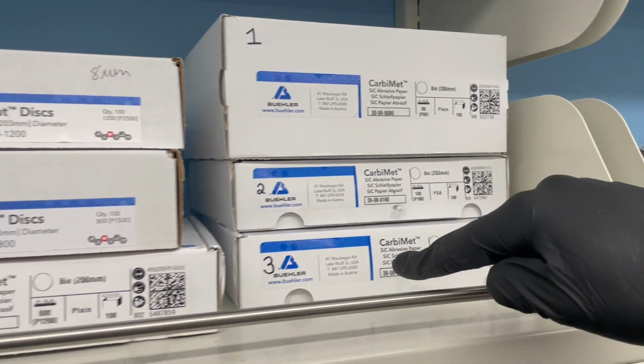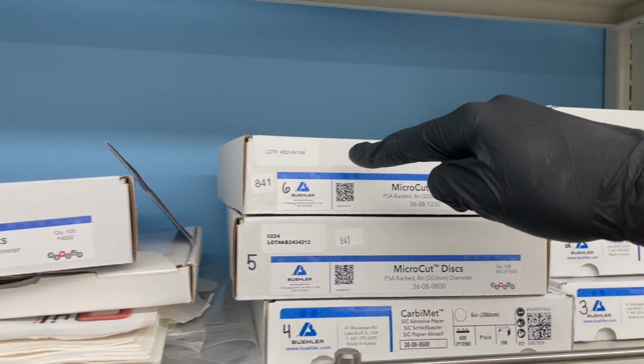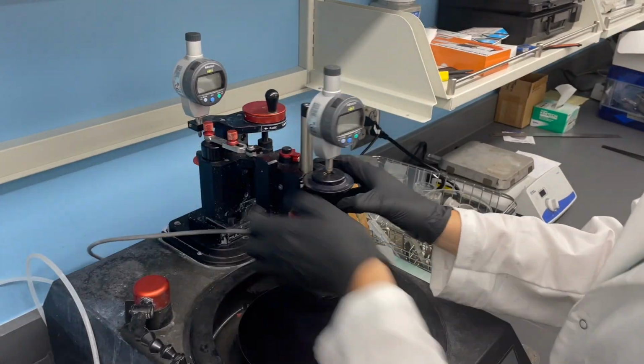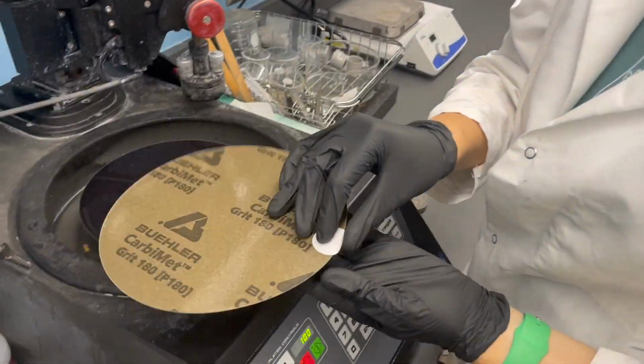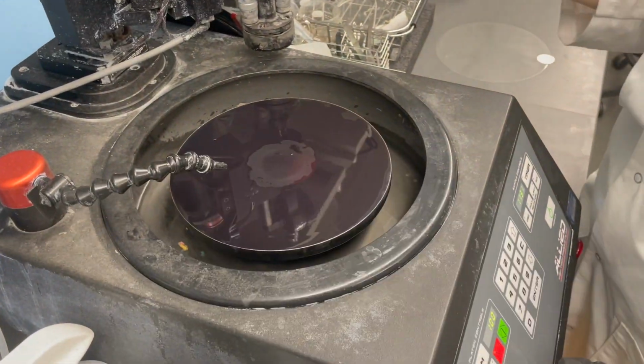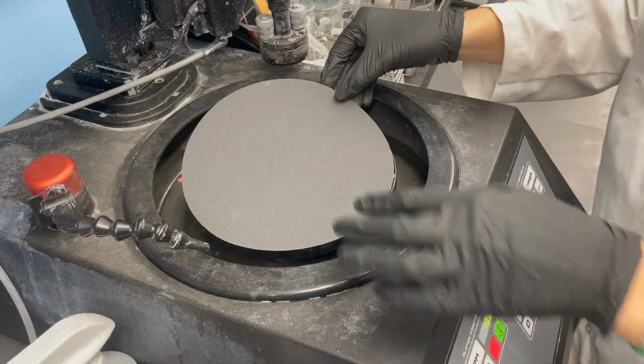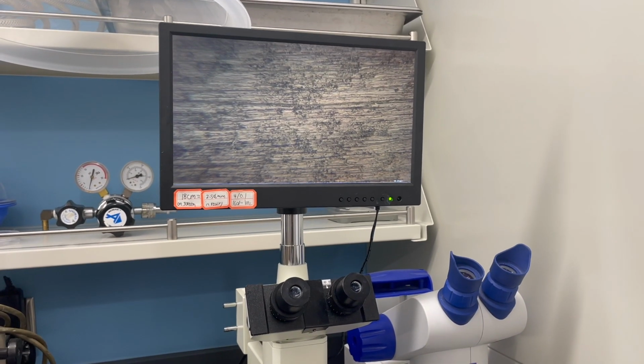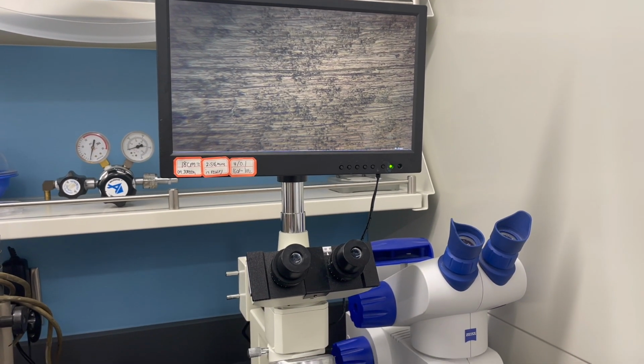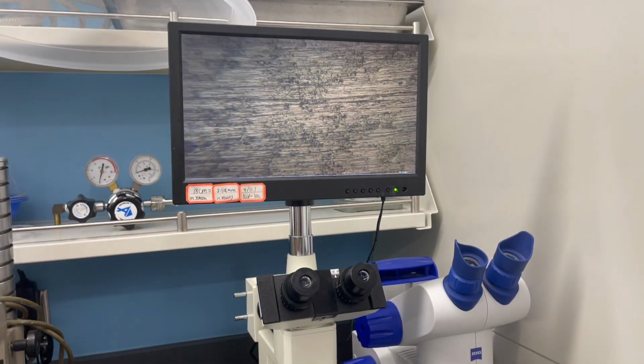Follow the numbered boxes to go from the largest to smallest grit throughout the polishing process. For some of the other grit papers in the progression, lightly wet the platen and peel off the adhesive and press the paper down. In between each grit, use the optical microscope to ensure all the grooves are going in the same direction and no outlying scratches are present.